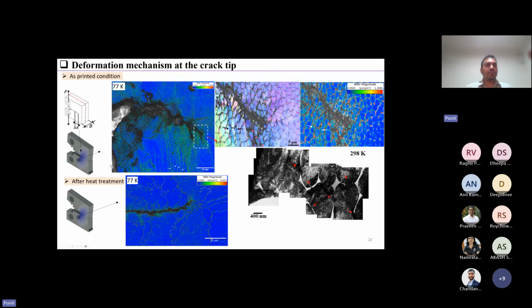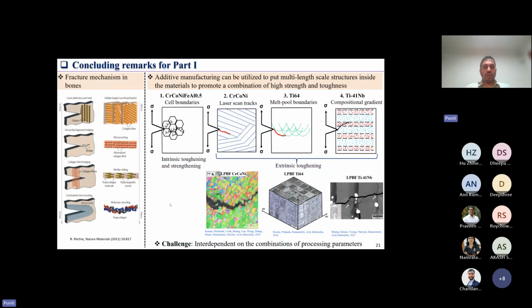Comparatively, if we look at this heat treated material, we see that this strain map shows dislocation activity only about 10 to 20 micrometers near the crack tip, and these dislocations are not able to travel away from the crack tip, giving you a much lower fracture resistance in this microstructure. So with these two examples, I come to the concluding remarks for part one of my presentation.